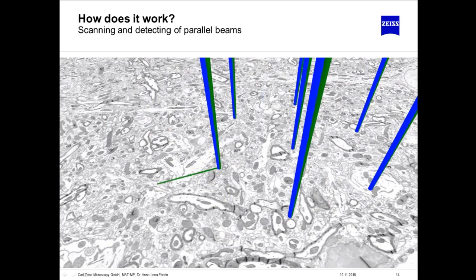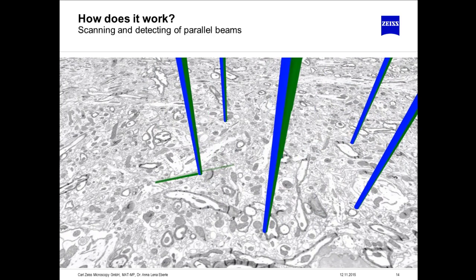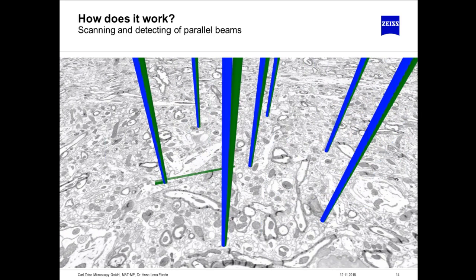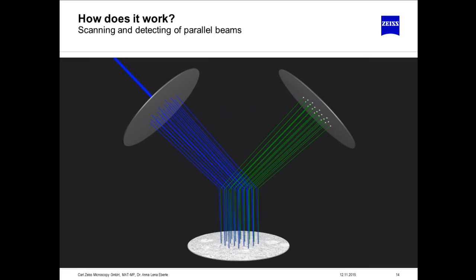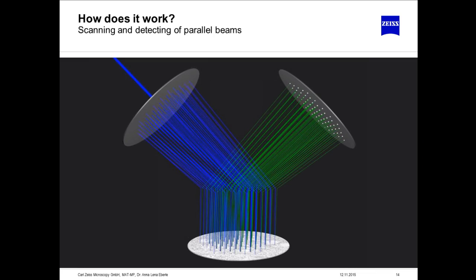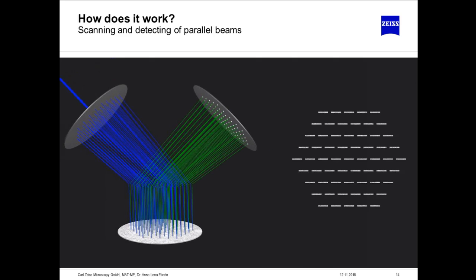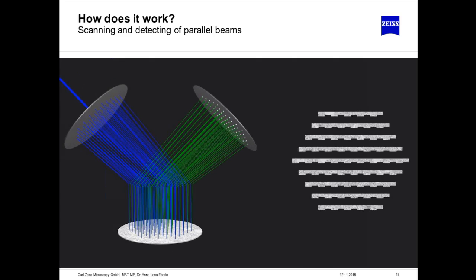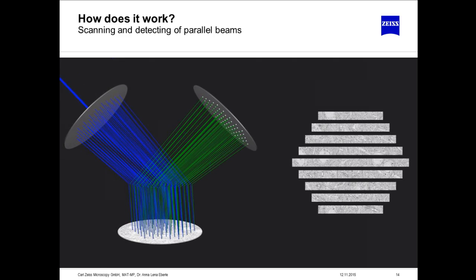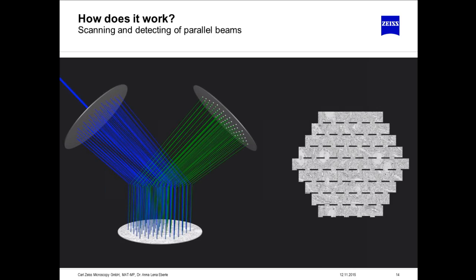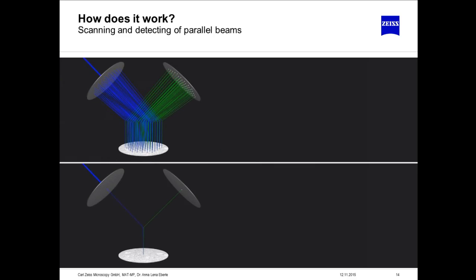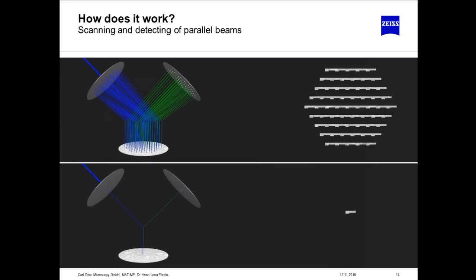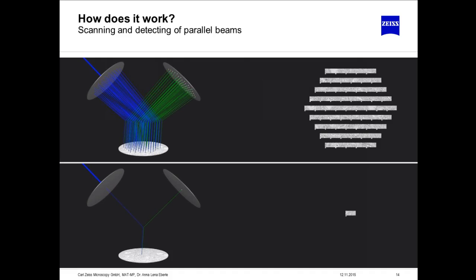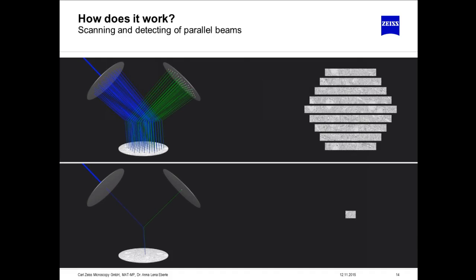The signal electrons that are generated on the surface while the beams scan over the surface are projected onto a scintillator, which is shown on the right. And the changes in signal intensity over time while scanning over the sample surface are detected from the backside of the scintillator with an array of detectors, namely one detector per beam. And these, in the end, generate the individual images of the individual beams. So, just to compare that to a single beam SEM, in the same time that a single beam SEM would take to image the small area in the center, the MultiSEM images the whole large field of view at once.